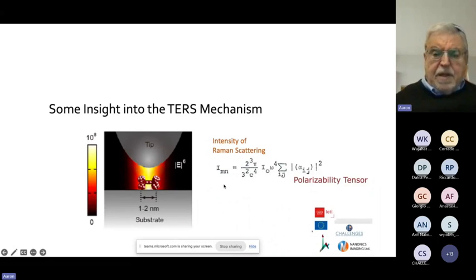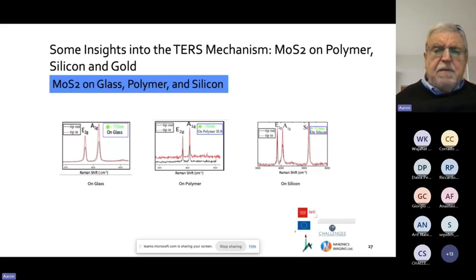Because the intensity of Raman scattering depends on the intensity of the initial beam, with the wavelength to the fourth, like any scattering method, and the polarizability tensor. And that's why the polarizability tensor has such a strong influence on what you see. So let's see if we can get some more insights into the TERS mechanism. This is molybdenum sulfide on three types of materials: on glass, on polymer, on silicon. I said on gold, I do have it, you'll see it in the next slide.